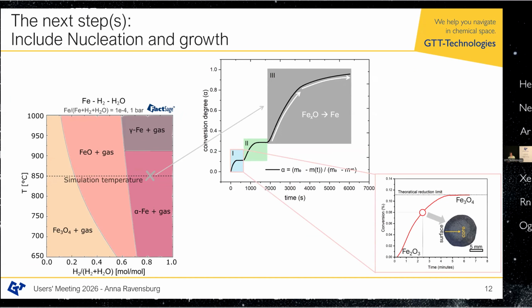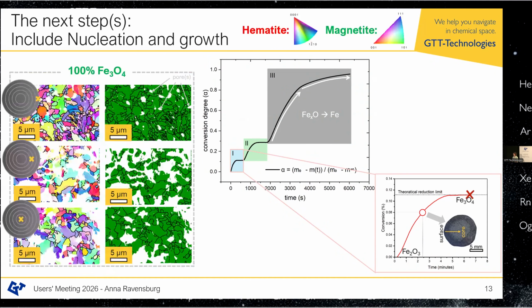And this is also what we are doing. Take out the pellet and look at the cross-section and look at which phases are stable at which point in time, which is an output of our model. So we can use this as experimental input for our model in order to confirm which phases evolve in which way and how to model the kinetics. And if we do this, we get these nice, colorful images. The left one is cool, and the green one is the interesting one.